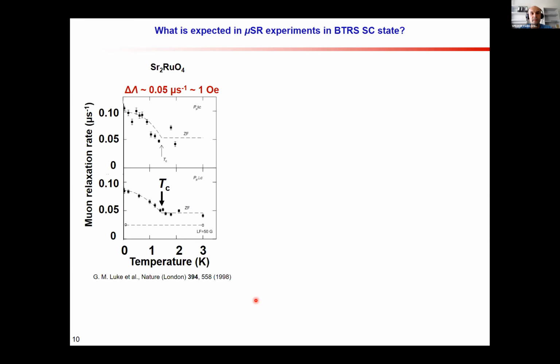So what are we looking for? Of course, the most well-known example is strontium ruthenate, and time reversal symmetry breaking superconductivity in this compound was discovered using muSR, muon spin rotation experiments, where it was observed that the muon spin relaxation rate enhances below the superconducting transition temperature. And this enhancement was related to the appearance of additional fields caused by the superconducting state.